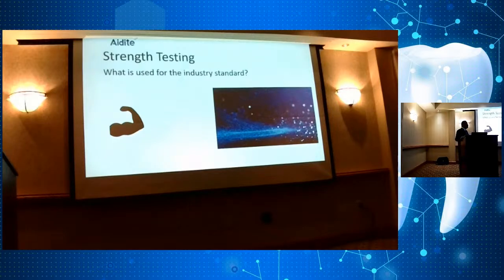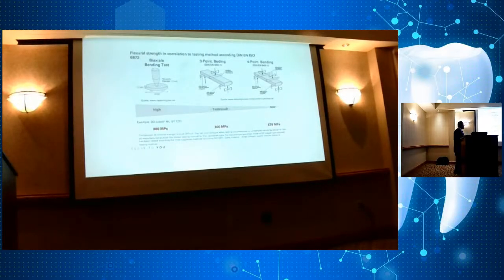Okay. So industry strength-wise, we do a lot of flexural analysis tests. The two main components of testing is biaxial flexural strength. You don't really need to know a lot of this information, but just know that we use two types of testing predominantly, biaxial bending test as well as the 3-point bending test. Okay? These tests are relatively the same, relatively speaking. You get very high results when you do the biaxial test.